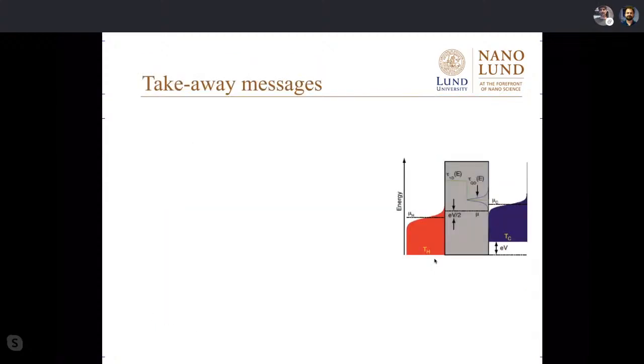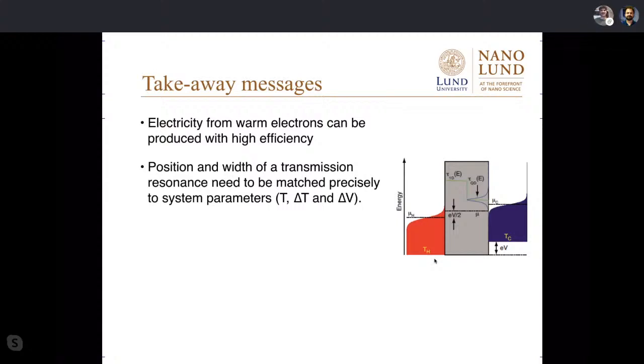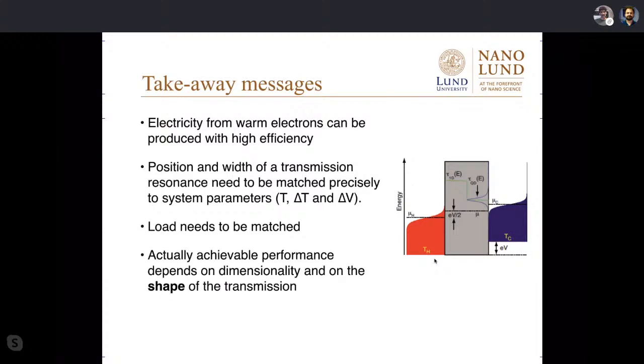So that's quite interesting. The takeaway message in terms of what I really want to say here is, yes, we can produce electricity from warm electrons with high efficiency, but it's not something that comes for free. We are talking about very specifically chosen working points that depend on T, delta T, and delta V, the voltage difference. You also need to match the load, so you cannot just use any load for any given quantum dot. They need to be matched. And if you really want to push to higher power, you really need to think of the shape of the transmission function. It's possible to do this, but it is not something you get for free. Sometimes people do experiments with thermoelectric materials where they put some quantum dots in there and hope for something magic to happen, but it doesn't happen, not just like that.